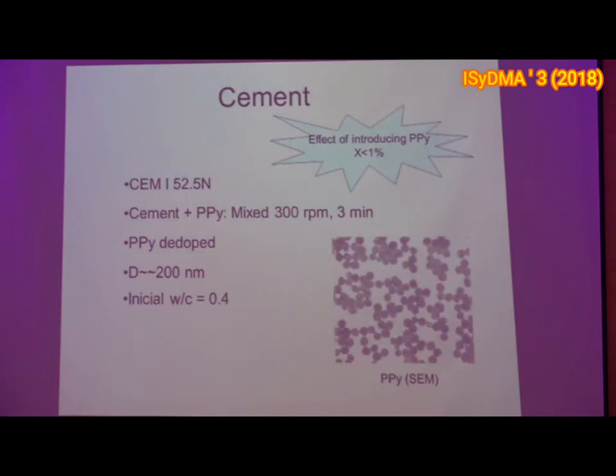So, second experiment. This is we try with the cement. This is the type of cement. And in this cement, we try to put polypyrrole particles, very, very small particles, about 200 nanometers. This is the diameter of these nanoparticles of polypyrrole. We start with a water-cement ratio of about 0.4, that is normal for the industry. And then we want to see what happens during the cure of the cement.